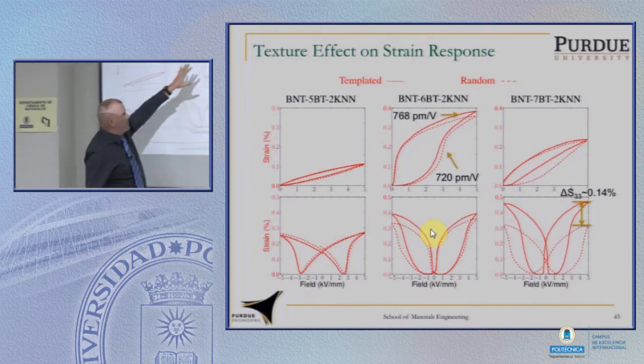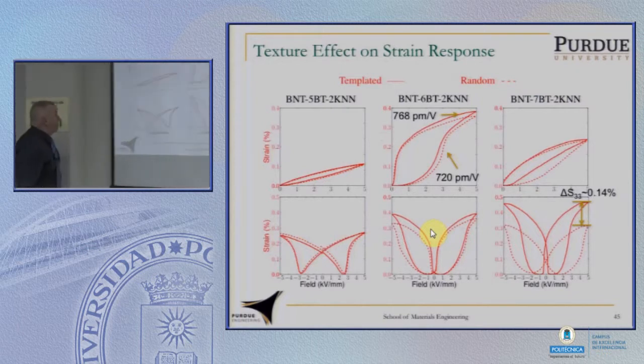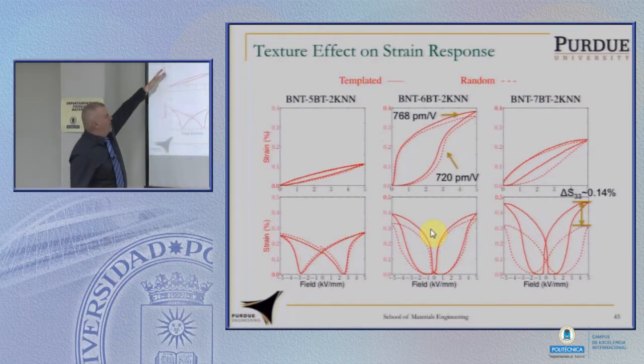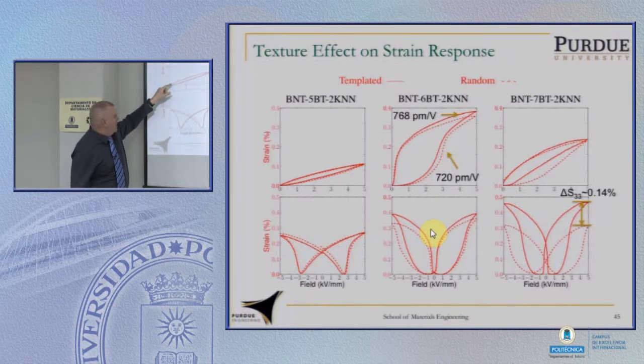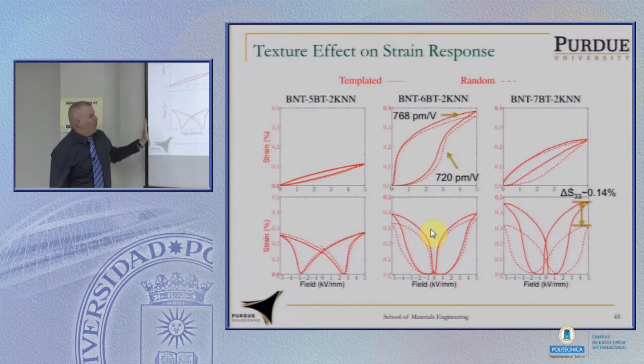Templated means textured or preferred orientation. Random means materials where we didn't introduce a preferred orientation. This is the strain behavior. So this is strain versus applied field for unipolar loading. So this is actually just going one direction. And this is for bipolar loading, which means we apply a field and we sweep forward and back.